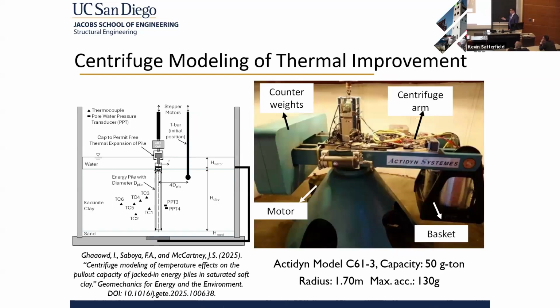So we again went to the centrifuge to try to prove this. We had an energy pile in saturated kaolinite clay. We had different sensors around the pile to measure water pressure and temperature, and a device to measure the undrained shear strength profile using a T-bar. This is the UCSD centrifuge in this case. So we spin the centrifuge up, install the pile, heat it, wait for these processes to happen, and then pull it out to measure the pull-out strength.